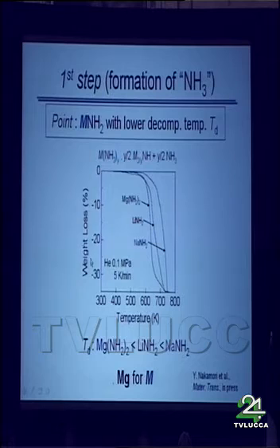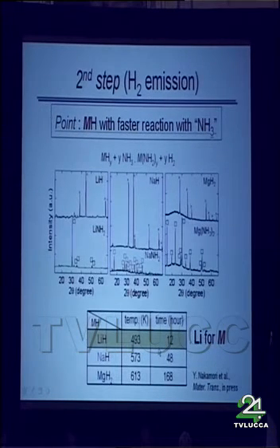And then we did an experiment. Here is a result of some thermogravimetry for sodium amide, lithium amide and magnesium amide. We can see the decomposition temperature is lower in this order. That's why we select magnesium amide here, magnesium for blue M. And for the second step, the point is to find the metal hydride having faster reaction kinetics with ammonia. We have confirmed that lithium hydride, sodium hydride, and magnesium hydride can react with ammonia completely. But the kinetics is very different. Lithium hydride has much faster kinetics, even at lower temperatures. That's why we have selected lithium for red M.